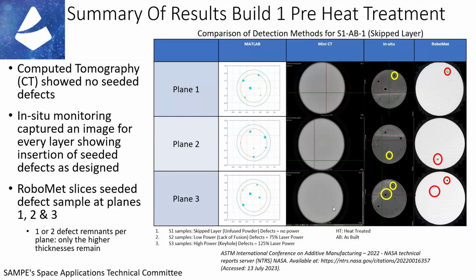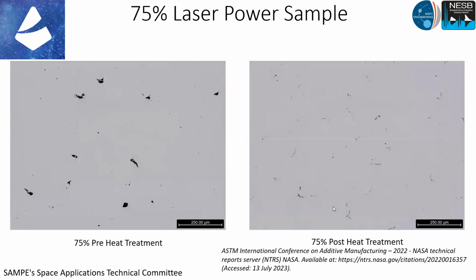But the in situ monitoring system at least picked up most of them, as well as a couple false positives. And then when we went through in the RoboMet, it's 100% hit or miss for the defects that we thought would be there. But we did take it a little bit further in that we made the samples, and then we did look at them with serial sectioning before and after heat treatment, as far as what is going to happen to these defects. So a lot of the defects, pre-heat treatment, were definitely visible, so we should have been able to see them in CT.